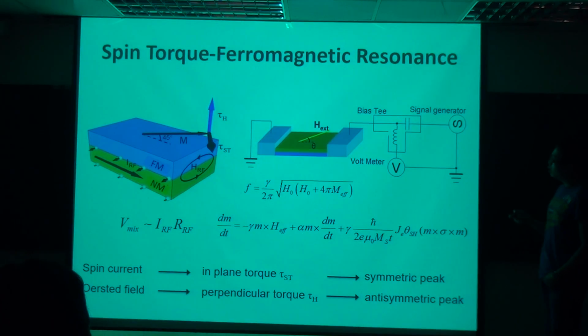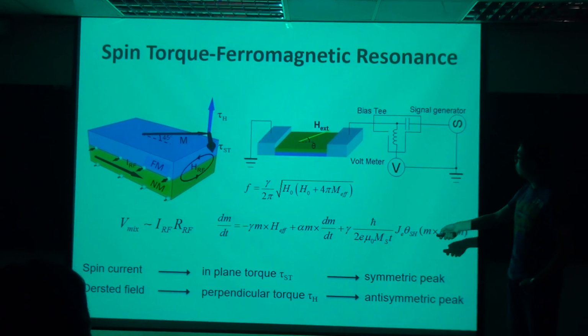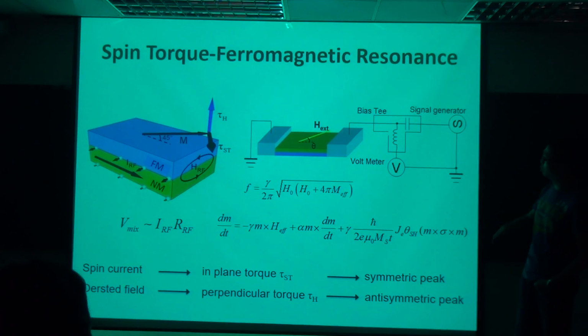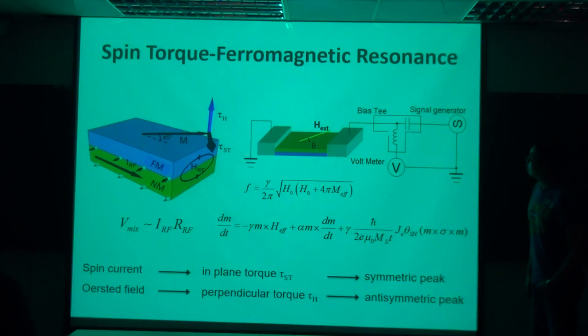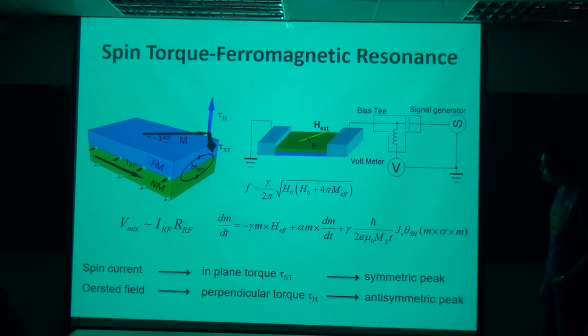And if there is a spin Hall effect, the spin Hall effect will give you a torque, which is the black arrow here, tau ST, which is in the plane. But at the same time, because you have a charge current flowing in the normal metal layer, that will give you an Ørsted field. And so the Ørsted field will give you this blue arrow, which is the out-of-plane torque. And these two torques will give you different symmetries in terms of FMR signal.